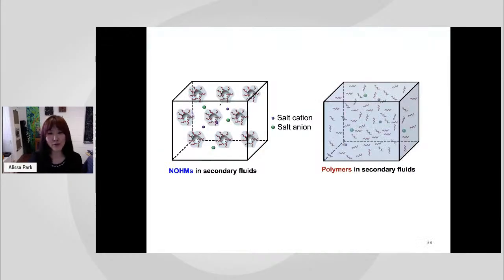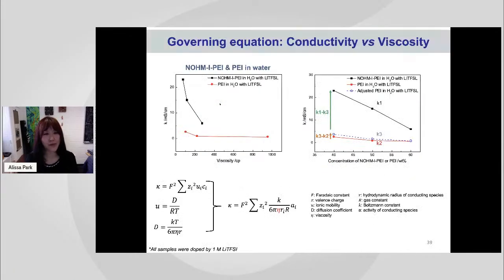So we went back to NOHMs and started thinking, okay, would it work? Can we use this as electrolyte? So let's think about two simple systems, one with NOHMs and one with untethered polymer, so same chemistry, mixed with, let's say, water as a base. Yes, you can, but I thought that the untethered polymer would be better as an electrolyte. But when we actually went to the lab and started testing these, this was exactly opposite to what I expected. If you look at the top left figure, it's telling you that the NOHMs-based electrolyte has higher conductivity and lower viscosity compared to untethered polymer. So we were getting really confused.